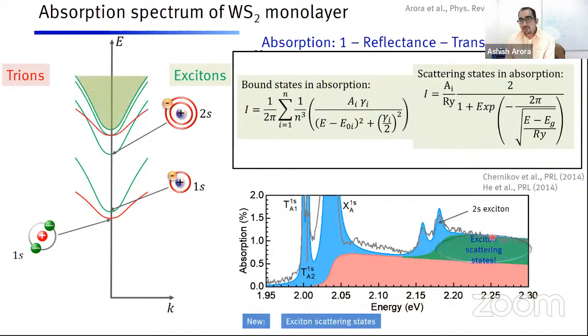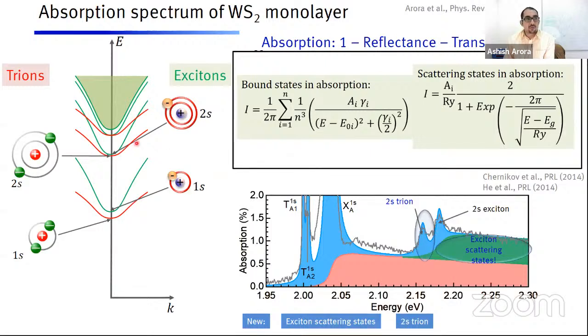However, what's new is that we start to see this step-like feature now. These are excited exciton scattering states, which were not seen before our work, because mostly people focused on reflectance spectroscopy, but one has to do careful absorption spectroscopy to start seeing these. And also there are further things. For example, there is this extra peak visible, which we tentatively assign to a 2s trion, or this excited state trion. So this is also new.